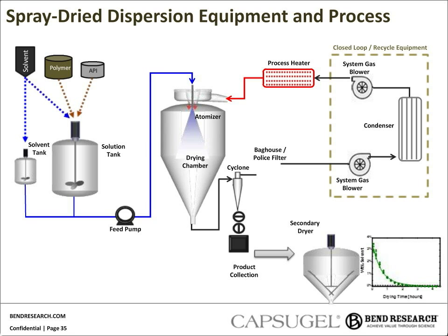Since the residence times inside the spray dryer are short, on the order of seconds up to maybe a minute at most, the SDD that comes out of the cyclone will have some residual solvent remaining on the particles. That residual solvent is removed in a secondary drying process, usually a tray dryer or an agitated conical vacuum dryer, with longer residence times that are more on the order of hours, in order to remove that residual solvent down to acceptable levels.